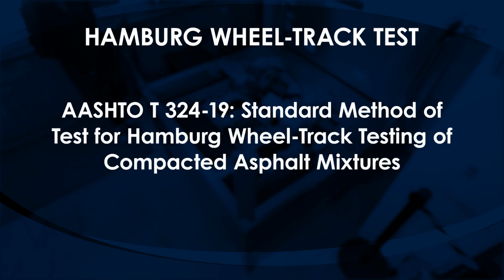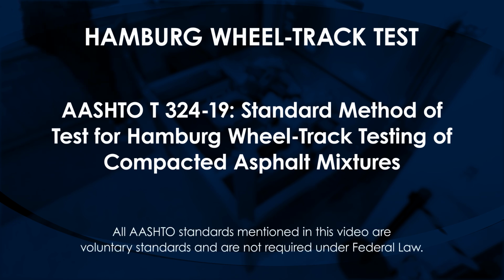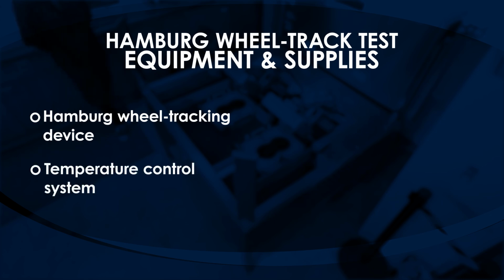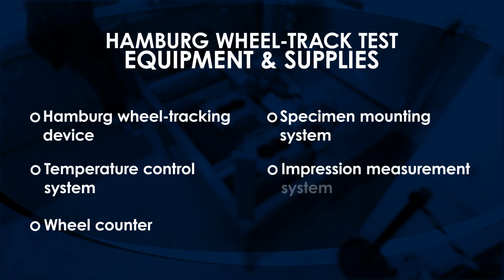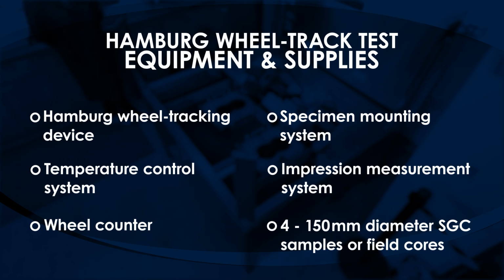The Hamburg Wheel track test is based on AASHTO T324-19, Standard Method of Test for Hamburg Wheel-Track Testing of Compacted Asphalt Mixtures. All AASHTO standards mentioned in this video are voluntary standards and are not required under federal law. Equipment and supplies needed for the Hamburg Wheel track test include a Hamburg Wheel tracking device, temperature control system, wheel counter, specimen mounting system, impression measurement system, and 150 mm diameter SGC samples or field cores.